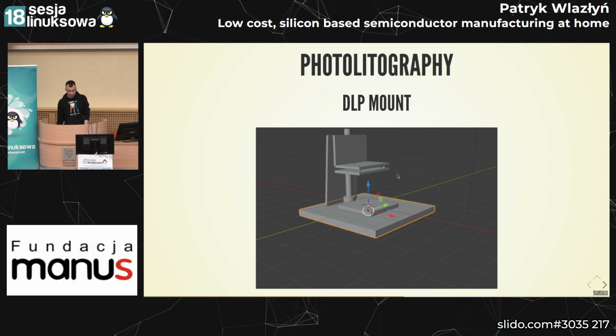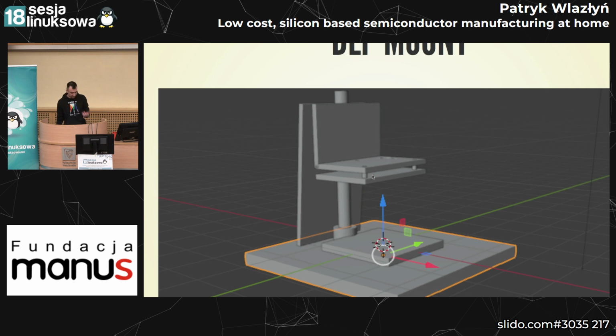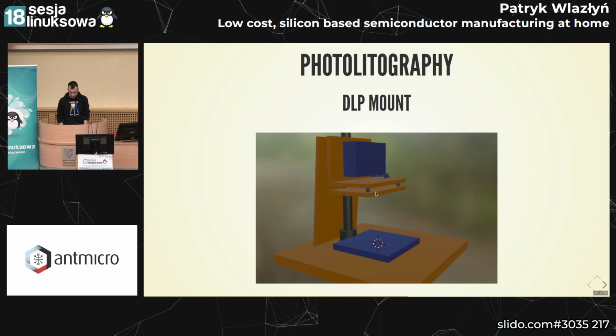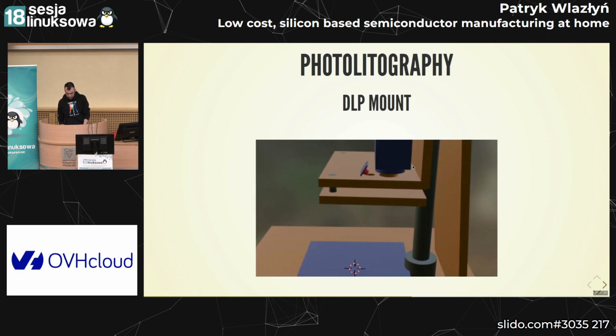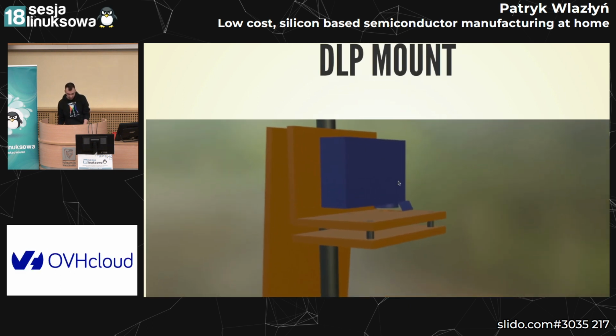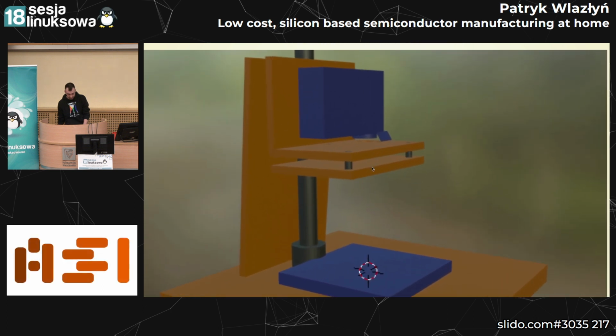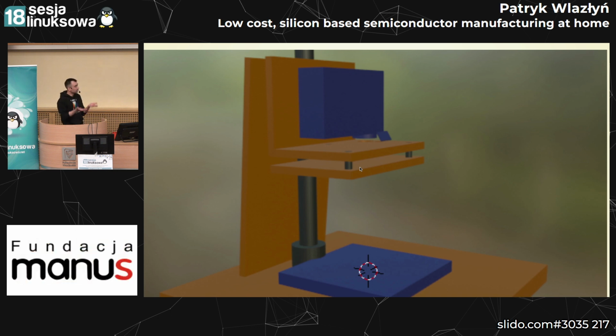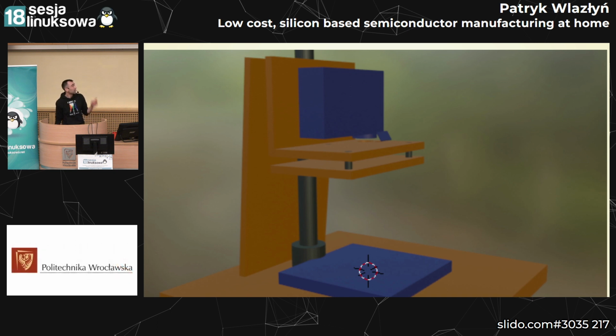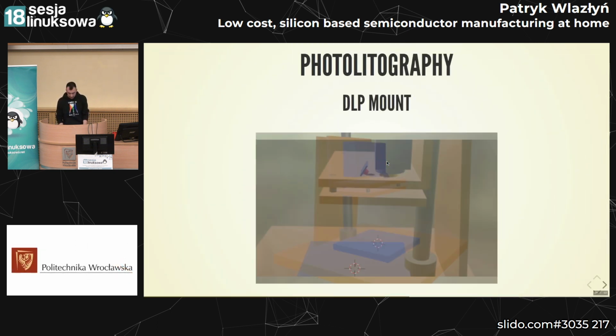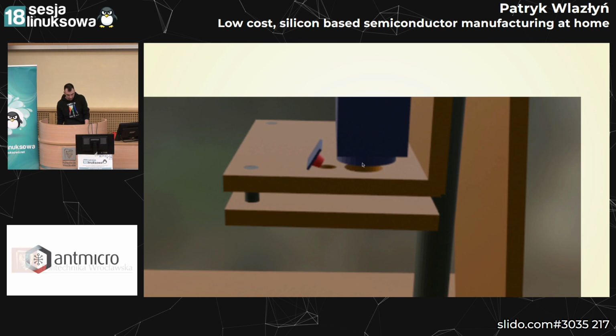This is the DLP mount. So this is a very simple setup. The DLP will sit on top of here. There is an opening that it will shine through, and we will put the wafers on the bottom plate here. So I have more pictures that will be showing this better. So we have a DLP projector on top, and we'll be putting the wafers here on the bottom plate. And you can adjust the plates with the screws, so you can easily find when the DLP is actually focusing the image correctly. Yeah, and you can see there is an opening for the DLP to shine through.